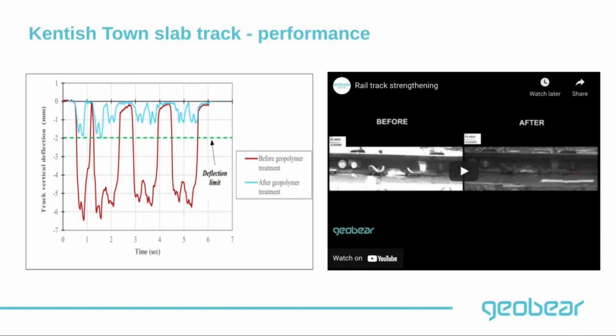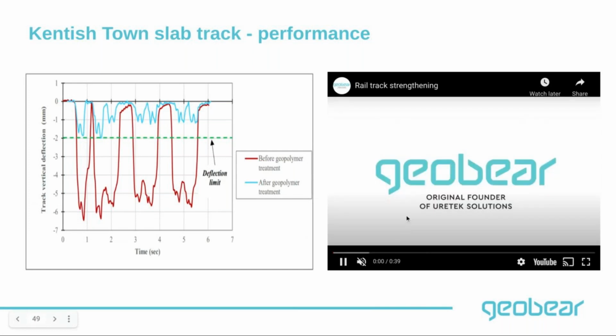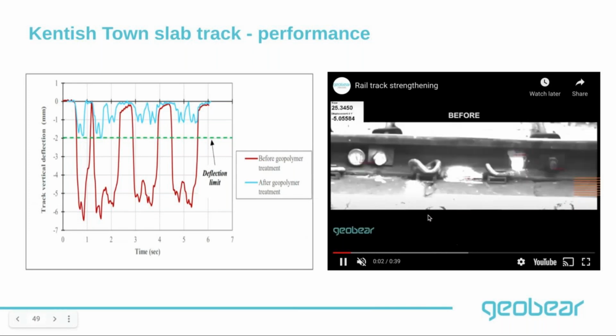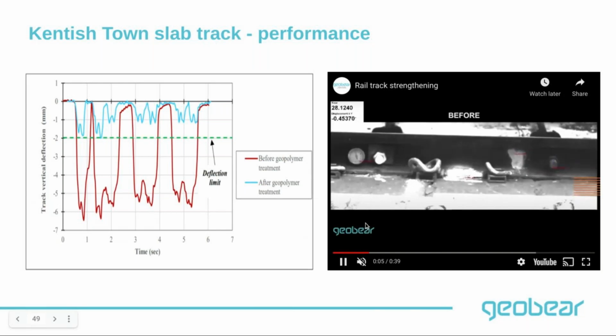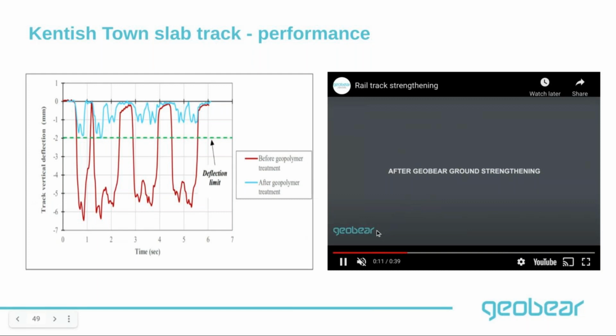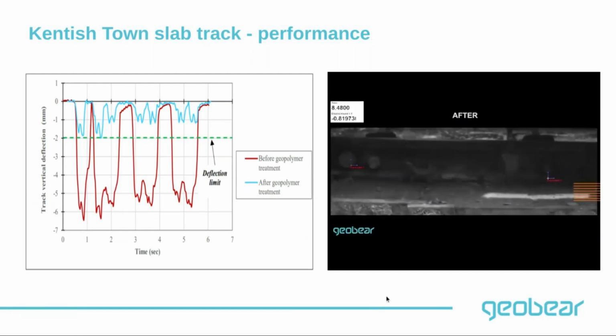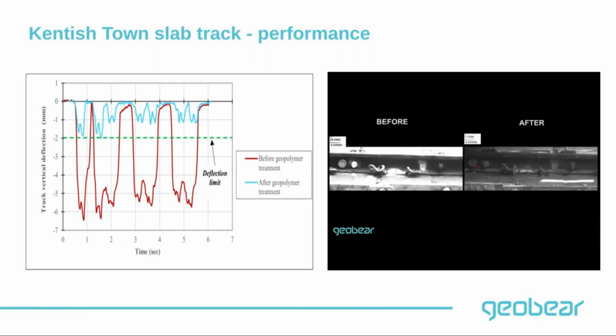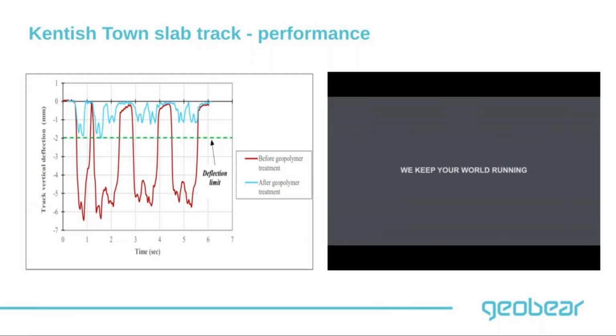Interestingly, it is the maintainer that actually carried out some deflection measurements before and after the work, and this is how the deflection looked before the treatment. You can see significant deflections being observed at that location, reaching up to 6 millimeters. And after we came in and carried out our injection, this is how the deflection actually looked, and we managed to reduce the deflection to 2 millimeters, so almost putting it right in the middle of the optimum range of track deflection.